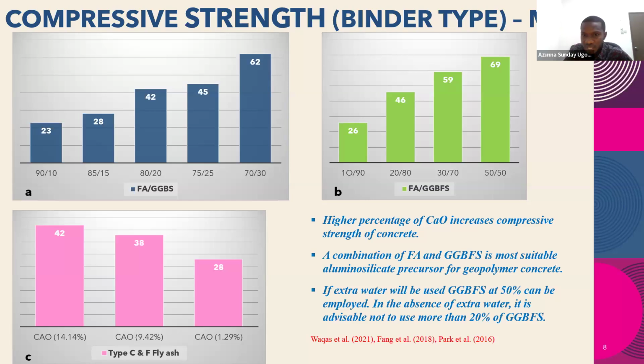So you can see it in virtually all of the literatures that we used. These are all different mixes, depending on the mix design from different literatures. So you have to strike a balance in your mix. And before you can do this, you must have a detailed understanding of the chemical composition of the binder you are using for your geopolymer concrete. You must know the percentage of calcium oxide in your fly ash or in your slag. You must know the percentage of silicon oxide in your fly ash and in your slag. So that is what will determine the percentage or the ratio which you mix them, because a combination of both is good.